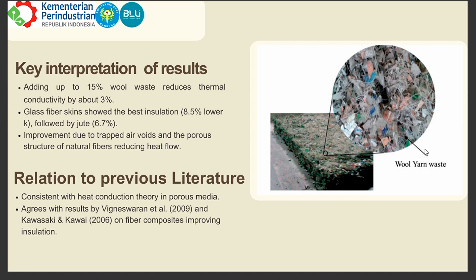Okay, so this is the key interpretation and relation to literature. The results align well with heat conduction theory in porous materials where air voids reduce heat transfer. Wool's crimp structure helps to trap air, while glass and jute fabrics act as barriers that limit heat flow across surfaces. These findings are consistent with Vigneswaran in 2009 and Kawasaki and Kawai in 2006, who also found that fiber-based composites lower thermal conductivity through increased porosity and interfacial resistance. In conclusion, the study successfully confirms that combining Tetra Pak waste with wool and textile fabrics can produce sustainable composites with excellent thermal insulation performance.